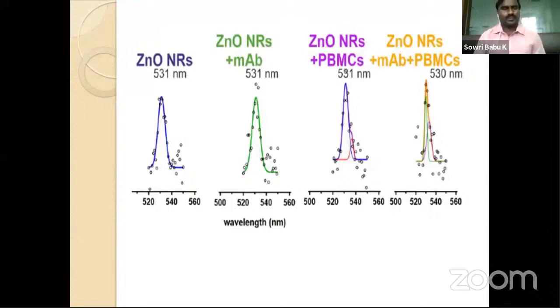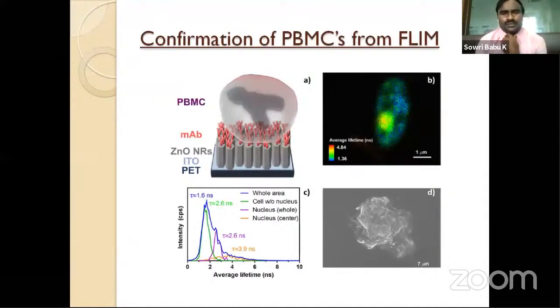As I told you, we have used indirect optical detection. That means these PBMC cells were loaded with acridine orange, and we have measured the acridine orange photoluminescence, which generally has emission in the green region. So we can see the variation of photoluminescence peak positions and intensity before and after the addition of monoclonal antibodies and cells. This is another confirmation where we can confirm the detection of these PBMCs by zinc oxide nanorod fluorescence lifetime imaging technique.